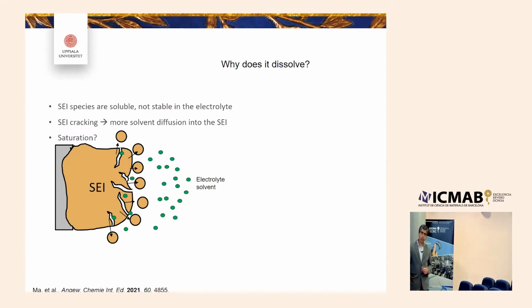The other reality is that when these SEI species dissolve, at some point the electrolyte becomes saturated by SEI species. So we try to understand at what point the electrolyte becomes saturated by SEI species, and whether there's a way to influence that to make the battery more stable.